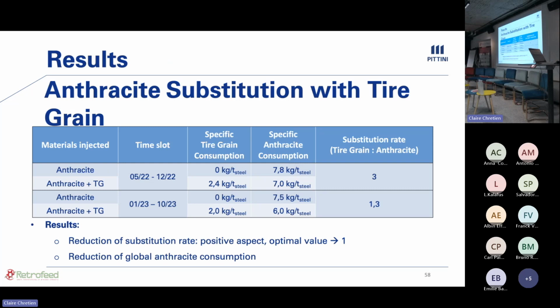So these are results in order to compare 2 years. And we can see that in the first year, 2022, we had a higher substitution rate, which means we were not able to manage the material properly. But in 2023, we enhanced our ability to inject these materials. So we lowered the value from 3 to 1.3. Those are, of course, the specific values of the materials compared to the liquid steel which is produced. And of course, one aim is to have this value at 1, which means that anthracite can be replaced at a 1 to 1 ratio with tire grains. But also one important aspect is that even if we are not using alternative materials, we are paying more attention to the anthracite injection in our furnace.